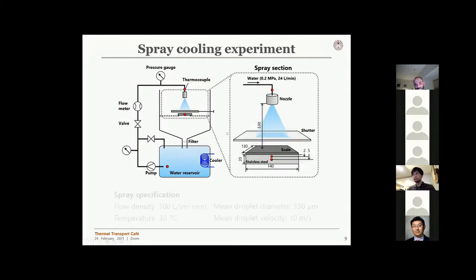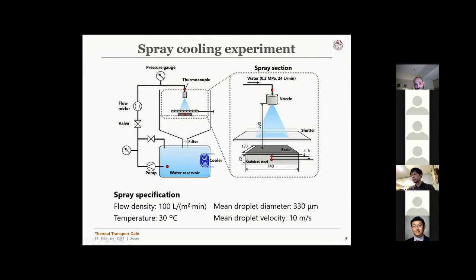Using this kind of setup, we have a water reservoir, and the water is pumped up to the nozzle, and from the nozzle the water is sprayed onto the plate. We have a stainless steel plate here, and we coated this stainless steel plate with some oxide materials.